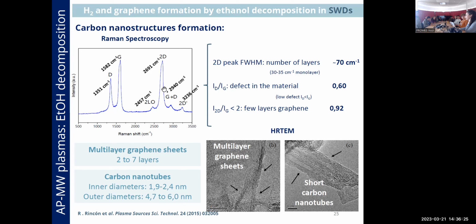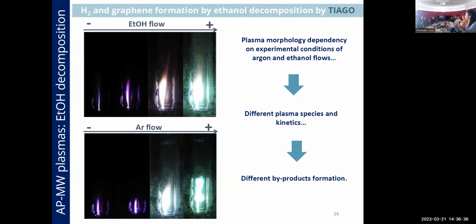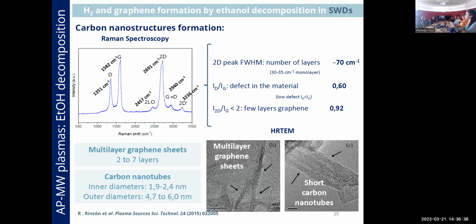So, just by having a look at the Raman spectrum, we can say that the bands related to the defects of the material are less intense than those related to the formation of few-layer graphene nanosheets, the 2D and G bands. So okay, we know that we have graphene-like structures in our material, but it is possible to quantify the number of defects and the number of layers of our material.